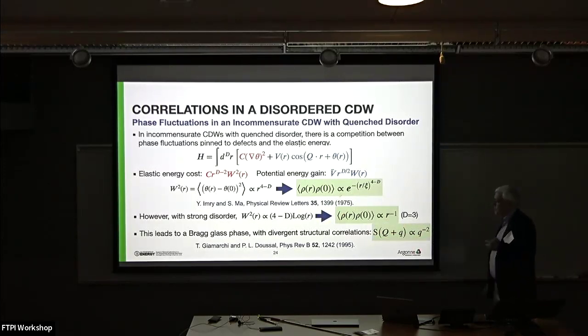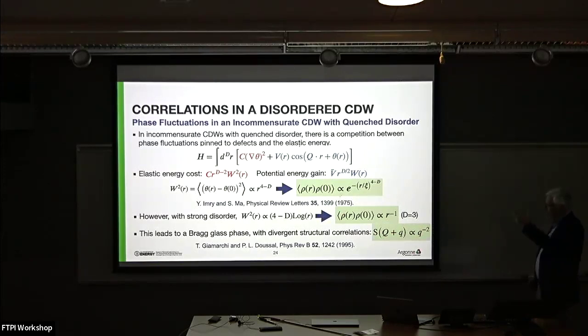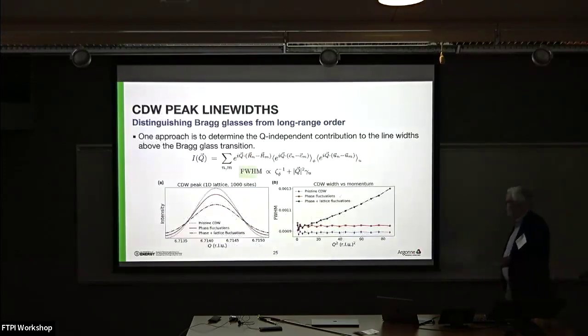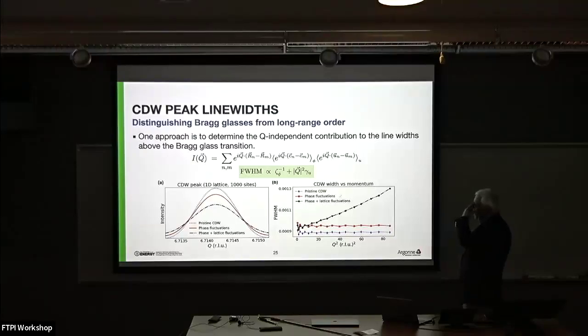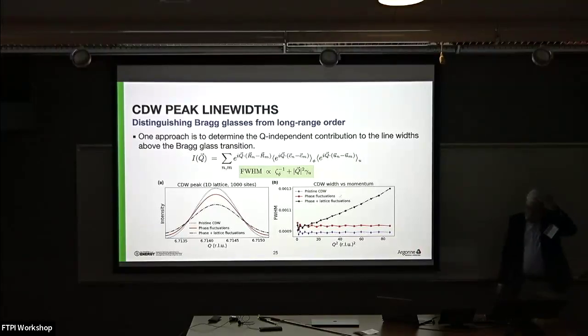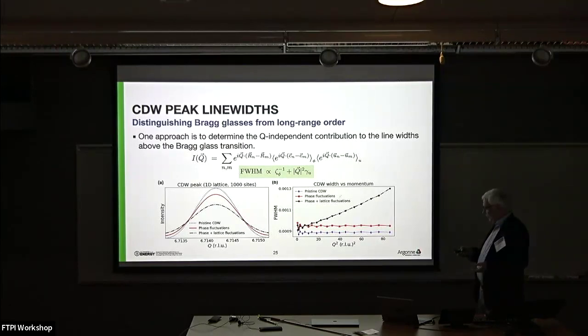So Bragg glass, the whole idea behind Bragg glass has been around for 30 years, but there are very few cases where people feel that they've confirmed it's true. And the approach that Una and Krishna came up with was, okay, we wanted to have a high throughput measurement that used the machine learning tools that we developed. And one high throughput method is to use the line widths of the materials.